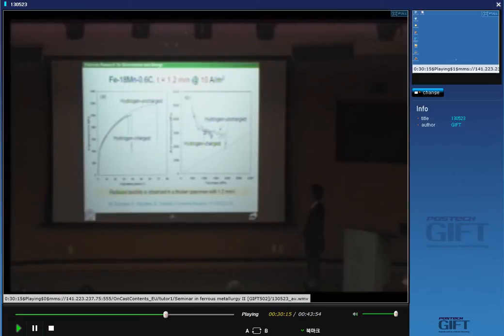This is uncharged condition, hydrogen charged condition. You can see reduced ductility in this case. I'm sure no change in yield strength and work hardening rate in the initial stage or early stage of deformation, but slightly changed in this region.